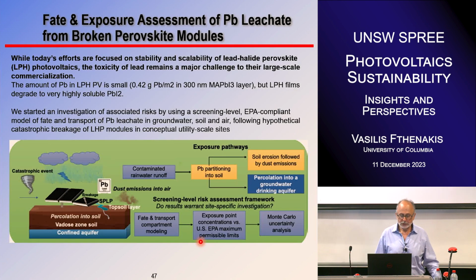Now, what else we should look at when we're talking about perovskite, especially the lead halide perovskites, and all the industry records that I showed before on single junction. They're based on methyl ammonium lead iodide. And you know that it has lead, okay? So with lead, there is an issue because lead is toxic. I think nobody has done fire testing of perovskites to see if lead is going to be retained there or not. Obviously, it depends a lot on encapsulation, but we don't have products there to test them. And the amount of lead is relatively low, maybe about 0.4 grams per square meter, versus cadmium in cadmium telluride, which is about 5 grams, and lead in lead solder in crystalline silicon is a little more than that.